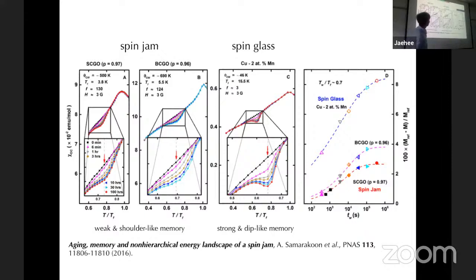Now we do exactly the same measurements on a canonical spin glass. This is now non-magnetic copper with 2% magnetic manganese atoms. And when you do exactly the same thing, this color coded, for instance, this violet is only waited 6 minutes.